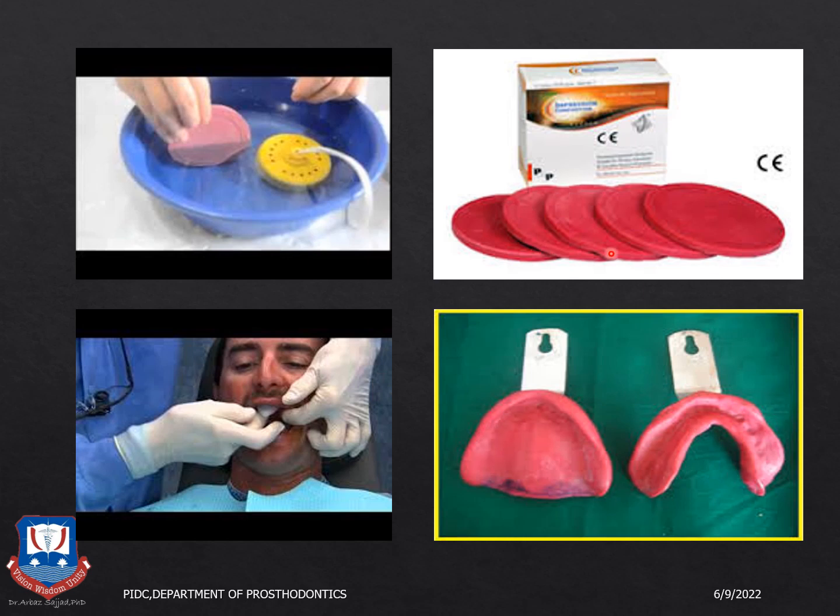As I said, this is a thermoplastic impression material. We get impression compound cakes like this. These are then tempered in a hot water bath, and then they are kneaded into a ball, which is then placed in the non-perforated edentulous stock impression trays, and the impression is recorded. You have to move fast because it starts getting hard soon upon removal from the mouth.